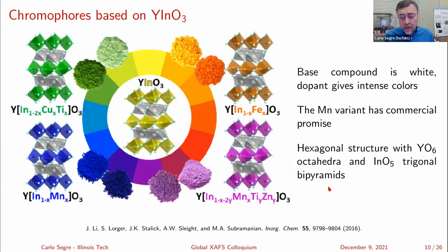So it's a hexagonal structure with YO6 octahedra, and they're very flattened octahedra. In fact, sometimes when I look at this structure, this oxygen atom here becomes part of the yttrium polyhedral sphere or coordination sphere, and so it might actually be 7 coordinated rather than 6. It's very close. It depends on the structural twisting that you have. And then you have indium O5 trigonal bipyramids. And so these have a threefold symmetry in the structure. And that's why you get these beautiful colors, because you don't have an octahedral environment for indium.